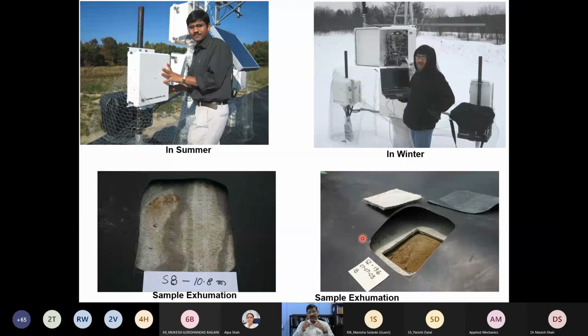That means that while selecting a geomembrane or a GCL, from a polymer chemistry point of view, not the physical property, not the mechanical property, you have to really give high priority to the chemical properties. One is crystallinity, melt flow index, OIT value. All these 3 parameters, and stress crack resistance, are the crucial parameters when compared to the tensile strength. Tensile strength comes out of the polymer matrix. Everybody uses the same polyethylene, but only that 5% to 10% antioxidant package decides the cost of the geomembrane and the service life of the geomembrane, not the 90% backbone regime. Backbone regime, anybody can fabricate.